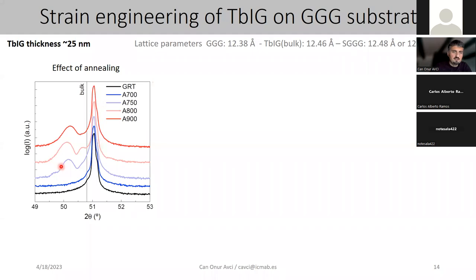corresponds to the bulk terbium iron garnet, which is absent at room temperature, because these films need to be grown either at high temperature or annealed at high temperature to get the correct crystal phase. So what I'm showing you here is that the room temperature or 700 degrees Celsius annealed films don't show any crystal structure. So they are either amorphous or polycrystalline. But starting from 750 degrees Celsius annealed, you see these large peaks that correspond to the strained terbium iron garnet. I say strained because the peaks do not correspond to the bulk value, but rather something on this side, which basically means that they are strained.